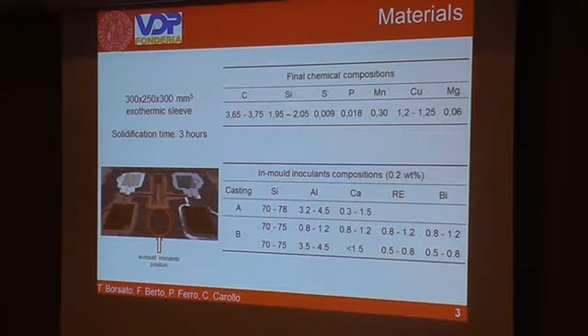The castings we produced were blocks with a section of 300 millimeters by 250 millimeters, 300 millimeters high, with feeders on the top surface. Such dimensions were chosen in order to increase the solidification time, which was about 3 hours. The mold contained 4 of these blocks and was made in sand. The castings had a common gating system to have uniform filling conditions.